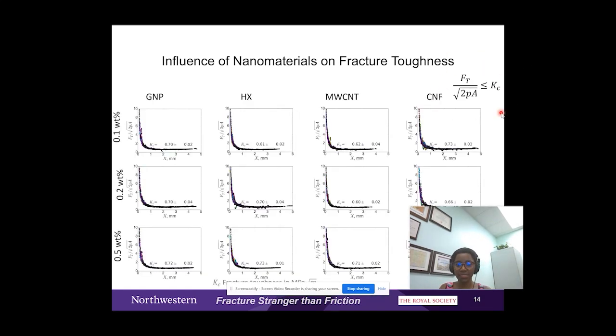So then I use my model to be able to assess the influence of nanomaterials on the fracture toughness. Now, according to my model, this quantity should be constant. And what I saw is that for very low values of the penetration depth, there's actually a mix of both ductile and brittle deformation taking place. However, when we go to very large penetration depth, then brittle failure becomes dominant, and in that range, we can then measure the fracture toughness.